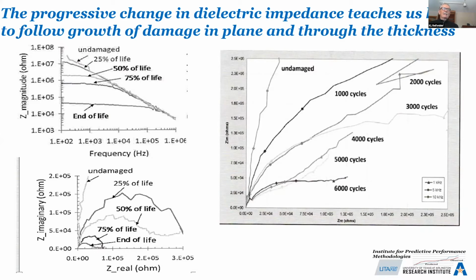So in the undamaged case, we get very little real transmission, but a lot of resistance, if you will, out of phase. And as I should mention, the frequency is on this diagram, bottom left. High frequency is here close to the origin. And as we go to the right, the low frequency response is on the right-hand side. So the size of these so-called loops, these are Nyquist plots for the electrochemical people in the audience, the size of these loops tells us the amount of polarization, how much this alignment is interfering with our attempt to oscillate the voltage. You can see that undamaged, we get quite a lot. That's an enormous loop. We only get a little of it. And at about 25%, you can see quite a bit of the loop. Towards the end of life, we get a very small loop, which indicates there's very little current by that time.